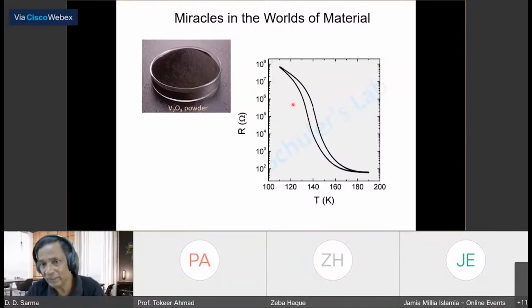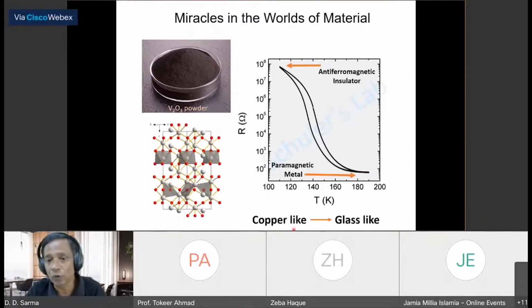And the same material, if I heat it up to 180 Kelvin, becomes such a low resistance. So you see that the resistance is changing by a million-fold, going from 10 to the power 2 to 10 to the power 8, just by changing the temperature. It is like taking an insulator and converting it into a metal, with a huge change in its properties. At this end, it's copper-like, it conducts as well as copper. At this end, it is as insulating as glass. It is the same material that, just by changing slightly the temperature, can go from a metal to glass-like.